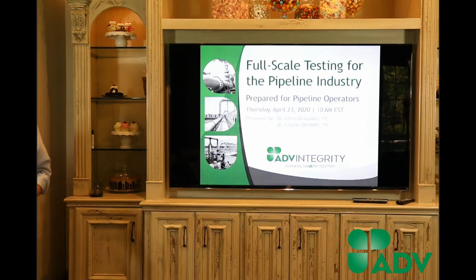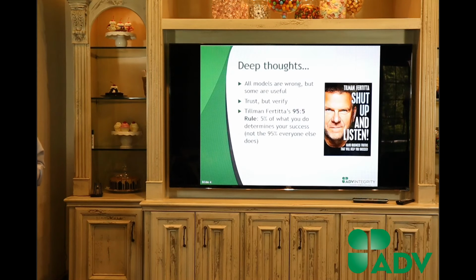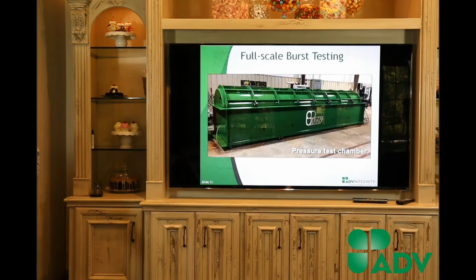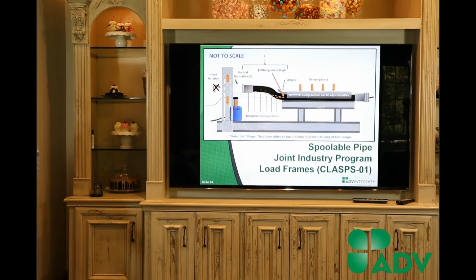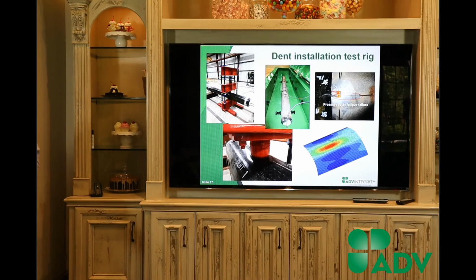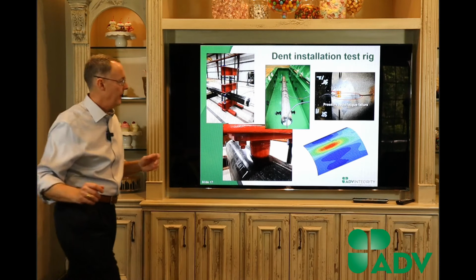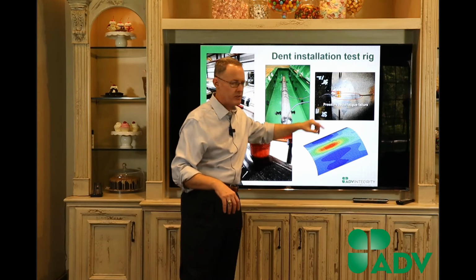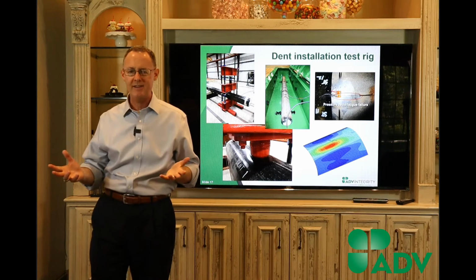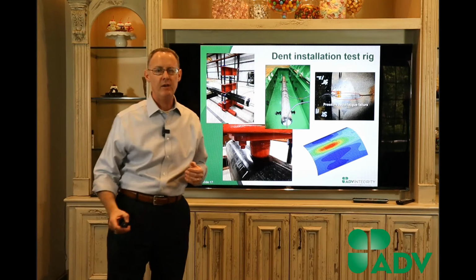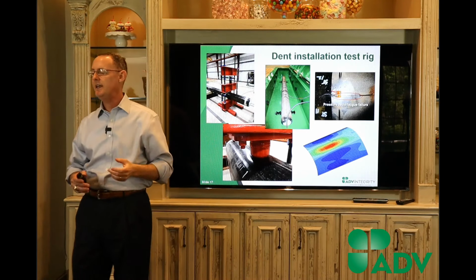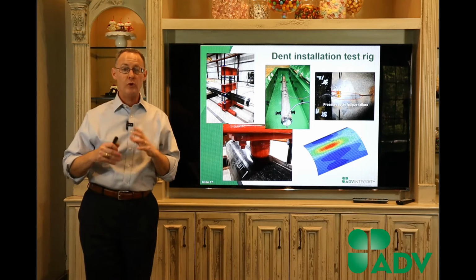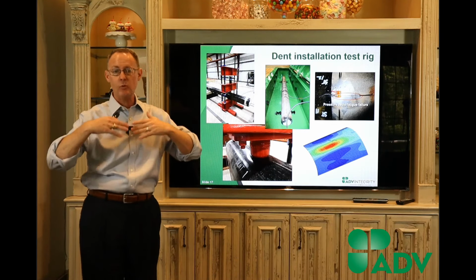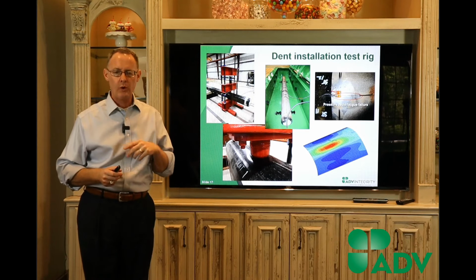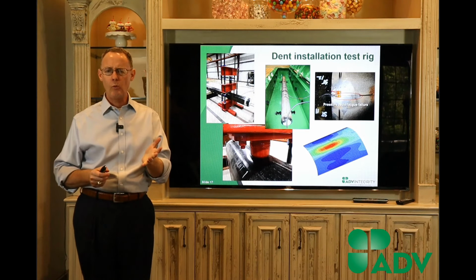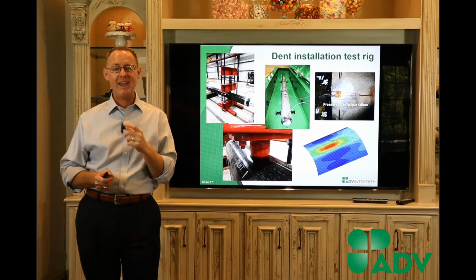Okay, here we go. So I was talking about dents. We've done a lot of dents over the years, and we've learned a lot. But the interesting thing is we're continuing to learn more. We'll put a strain gauge on it, and we will measure the strain. This is actually a fatigue failure that we get. If you know anything about dents, plain dents, the reason that it fails is due to fatigue and cycling. If we were to do a burst test on it, the first thing that happens is we basically just pop that dent out. So we're going to continue to do more. What makes dents often damaging is the interaction with mechanical damage.